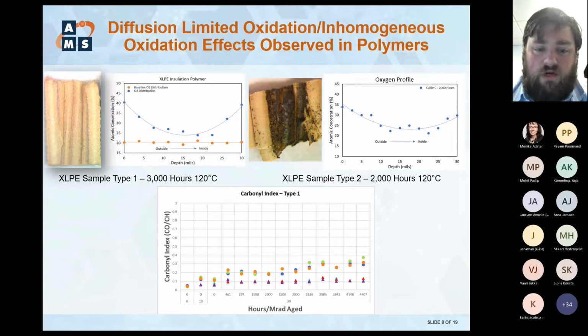And the circles, or the data points you see at the top, are actually carbonyl index values calculated from the exterior surface of the material, so the one that's in direct contact with the aging environment. And then the triangles you see are the carbonyl index values calculated at the middle of the material, so the most significantly affected regions in terms of diffusion limited oxidation effects.